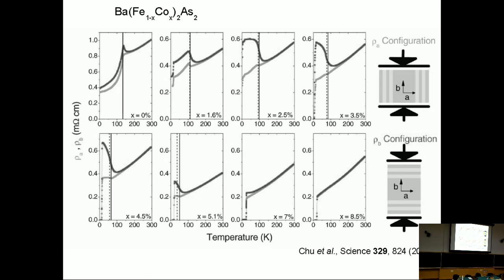And that's very impressive because the orthorhombic distortion itself is a very small and very slight distortion. It's about a 0.3% difference between the A and B lattice parameters. And in principle, since you already have a metal, it should not be expected to have such large differences between resistivity measured along these directions. So it was inferred that there is an electronic order that is somehow responsible for this highly anisotropic resistivity in these materials.